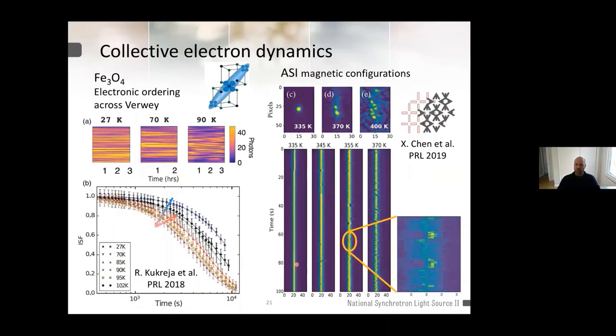It was proved also on other relevant cases, like the case of magnetite with the electronic ordering across, or around, I should say, the Verwey transition, where we clearly saw that at lower temperature we have a more static order, fine. Then you warm up and the dynamics accelerate, but finally it slows down before making the transition to happen,